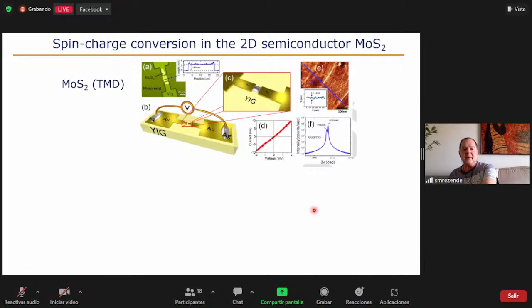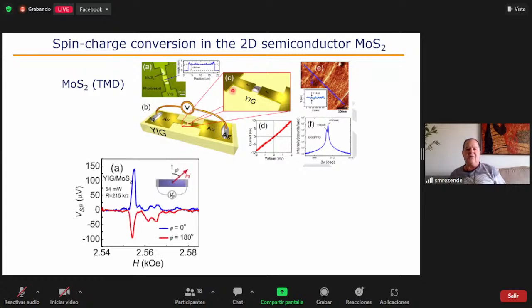Another topological insulator. We also did the experiment with a two-dimensional semiconductor, molybdenum sulfide. Again, this was made by Joaquim de Souza. He's able to obtain flakes of this material, and the flakes are placed on top of the YIG, with electrodes, and we measure the voltage by the spin pumping technique.